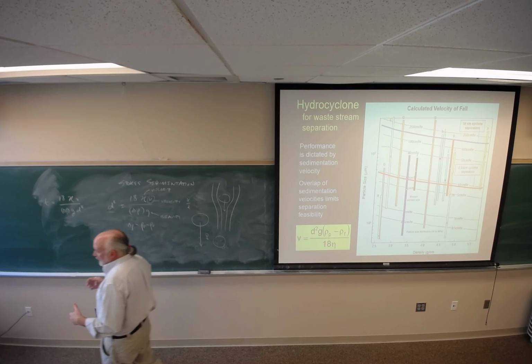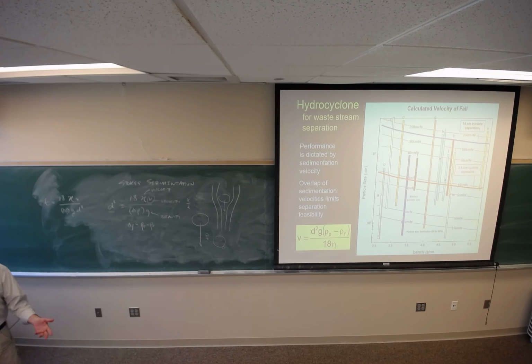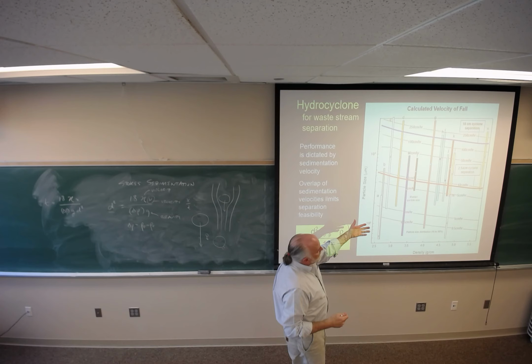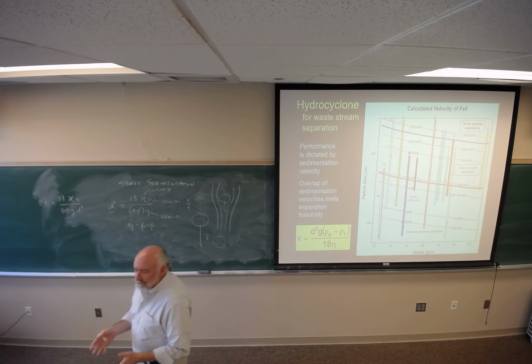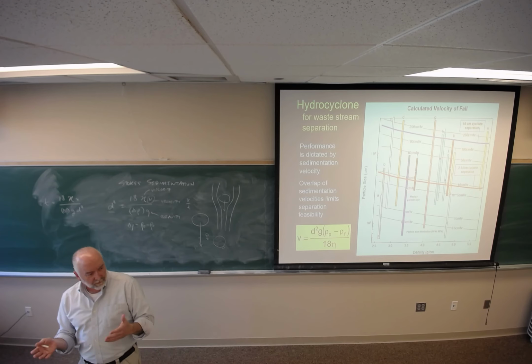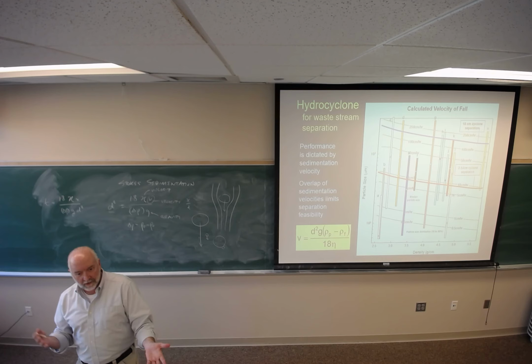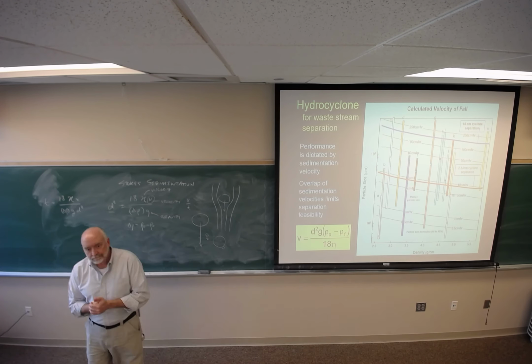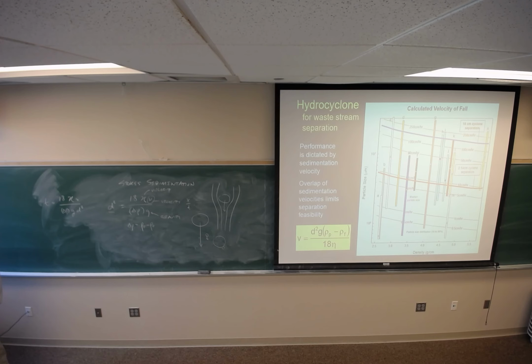That means that the coarse particles that are blue, which are represented by the top, overlap the finer particles of the red or whatever color that is over here, or the yellow at the end, and now I have a problem. If I put them in a hydrocyclone, I can't separate those particles because they are all moving at the same velocity based on the difference in size and density. Good? So that's the idea behind hydrocycloning. If the density of powders are similar, then you can get good separation. Or if the density of, say, the larger particles and the smaller particles and their sizes are sufficiently different.